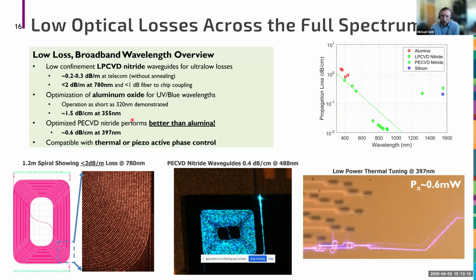And then kind of an exciting result even more recently is that we've been able to develop a silicon nitride recipe that performs really excellent at blue and UV wavelengths. So we're seeing on the order of 0.6 dB per centimeter at 397 nanometer wavelength. And then the performance of that film just kind of improves as you go to longer wavelengths. So we're down into the kind of few dB per meter type losses at 780 and near infrared wavelengths.